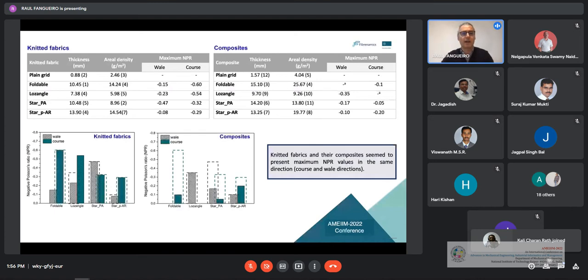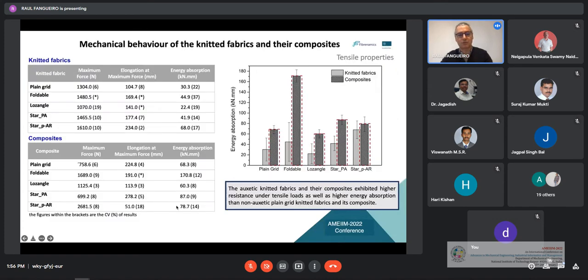And as you can see here, in terms of negative Poisson ratio, this NPR, we always have negative Poisson ratio in these fibrous arrangements. And then for just some of these structures, we convert this auxetic behavior from the fabric to the composite itself, which is quite interesting. And what is the effect of that? Because you have, for instance, the plane grid here in a composite material, in terms of energy absorption, you can almost have three times better for this foldable structure. So it means that in practical terms, we can really increase this characteristic of the material.